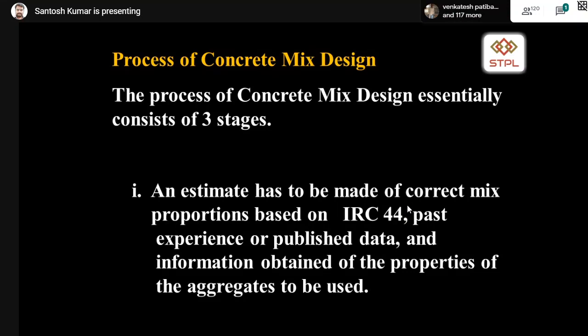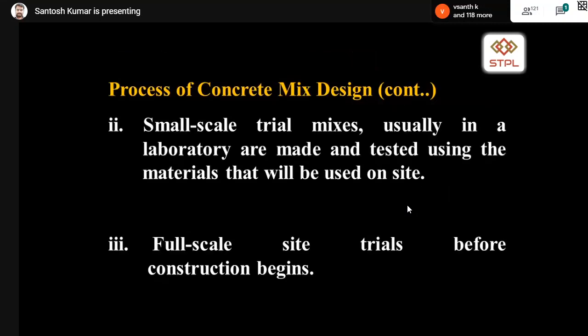First stage, you need to make a practical estimate about the mix based on IRC 44. And once the data is published, you need to take the properties of the aggregates, and then small scale trials shall be conducted in the laboratory. After that, full scale trials shall be conducted at the site before the construction begins.